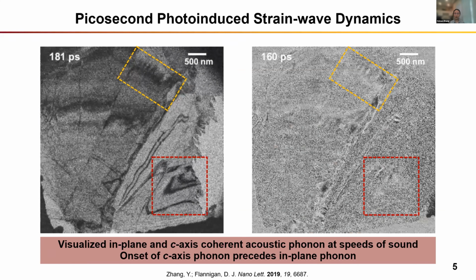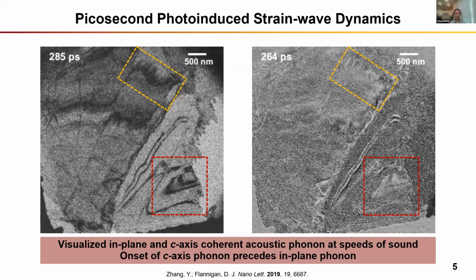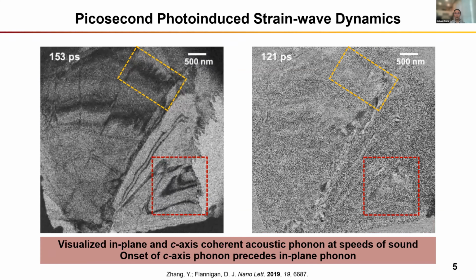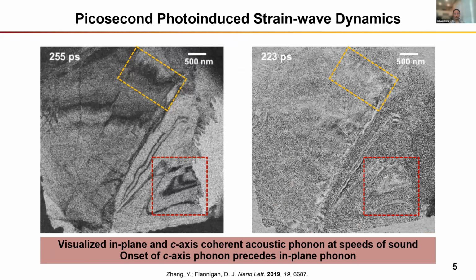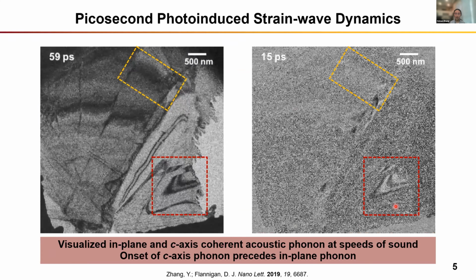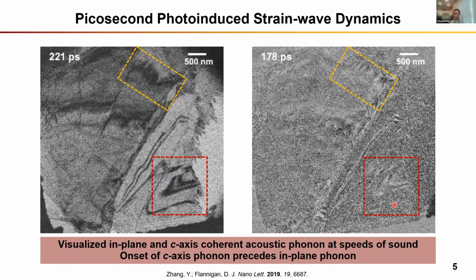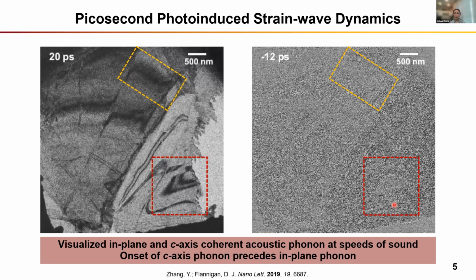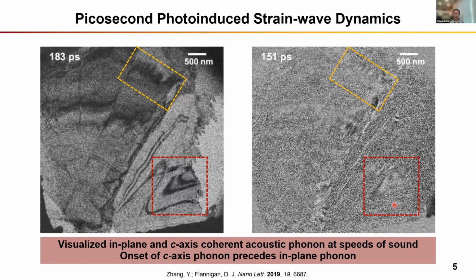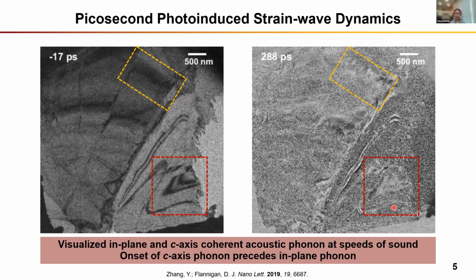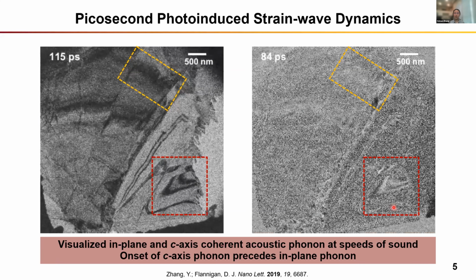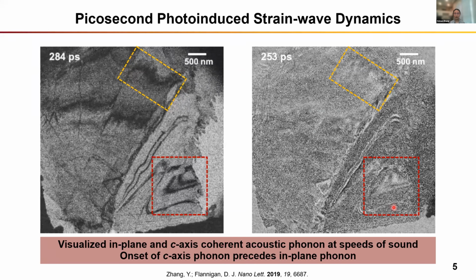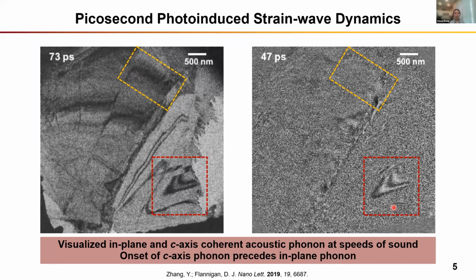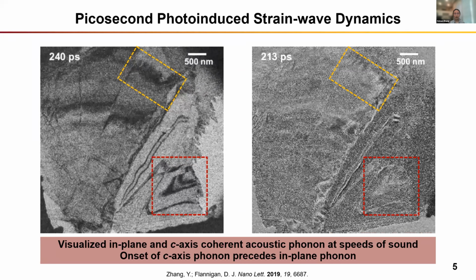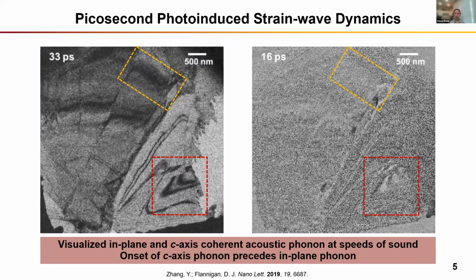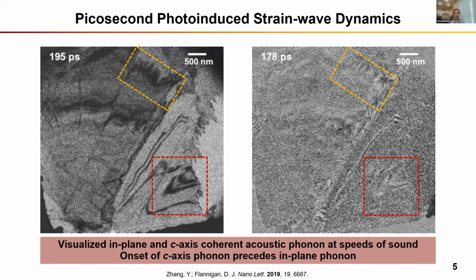On the right is a difference image series with the same time range. We can see in the video that the onset of the c-axis phonon precedes the in-plane phonon by just a few picoseconds. And this is likely due to this initial expansion of the layers along the z-axis following the photoexcitation, which leads to the launch and propagation of in-plane modes. This has been hypothesized and observed in simulations before, and we were able to directly visualize it in the experiment.